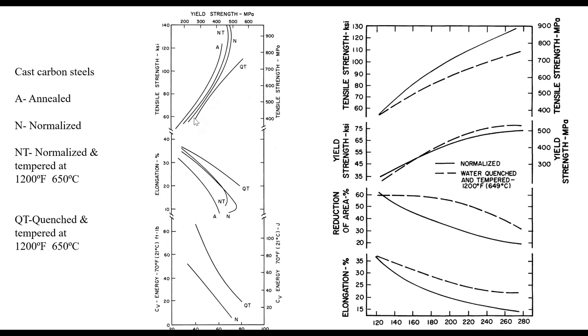The quench and temper gives me the highest yield strength for any particular tensile strength. It also gives me the highest ductility for any tensile strength and the highest toughness. So when I need the highest performance, I want quenching and tempering. Quenching and tempering sometimes causes cracking, and I need enough carbon in it, so those alloys tend to be more difficult to weld. If I need a plain vanilla, I'll get something that's normalized or normalized and tempered. If I need the optimal properties, I'll quench and temper.